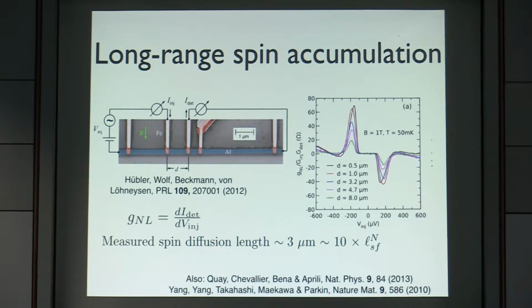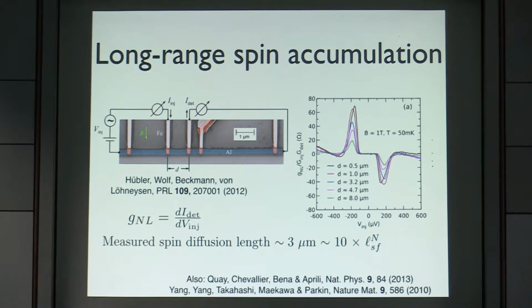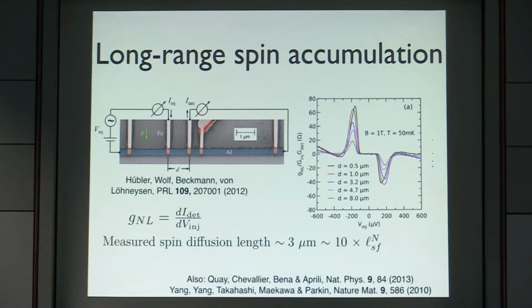Okay, our work started from a bunch of experiments some 5-6 years ago, studying spin transport in superconductors. And so here's an example of experiments. There were actually related experiments before this, but these were the ones which motivated us to do this study. So this is an experiment by the group in Karlsruhe. What they studied was set up like this. They had an aluminum wire superconductor connected to a series of ferromagnets. And what they did was that they injected a current on this loop, and then they measured a current on this loop. So this was a non-local measurement.